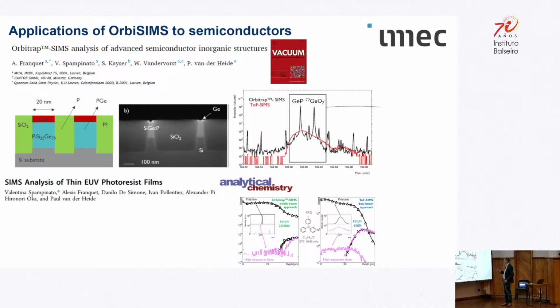They then took data, this is the TOF data, overlaid is the OrbiSIMS data. There's 2 things to take note of here. One of them is that obviously the Orbitrap data has got much, we can separate out all of these different peaks now. So we can separate out germanium phosphide from germanium oxide. By doing that, we can then do a depth profile from just those particular peaks, and then you don't have confounding chemistry, and that's how they can then get their quantification. This is a method that they call OrbiSIMS.